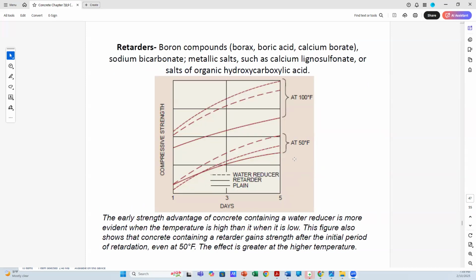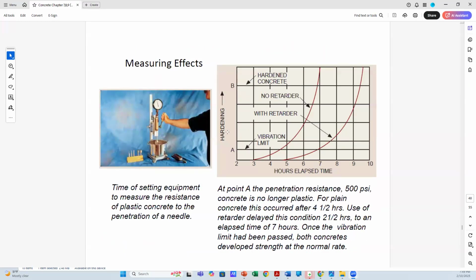This is the same study done under different temperatures. What you can do if you have to work in 100 degrees Fahrenheit. General concrete is poured within the 50-degree range. But if you have to work in the Vegas area or some warm area, the name of the game is the compounds or admixtures that you add, rather than water, to make the concrete workable in Vegas. A lot of measurements are done. There's a lot of tables. When you order the concrete in Vegas, you tell them that you're going to be pouring in 100-degree temperature, then they give you the right concrete, more expensive.